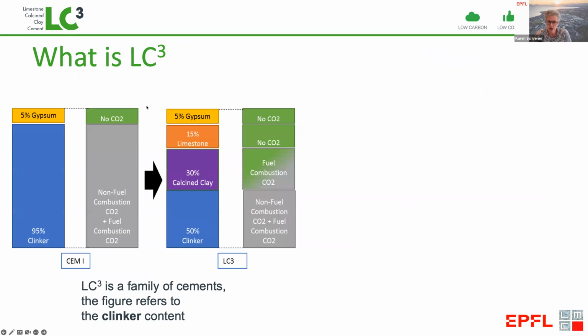Now, the reason we get this much lower CO2 is because we replace the clinker, which has very high emissions. We have a small amount of clinker we still have, but the calcined clay has much, much lower emissions, maybe only 1/10 of the emissions of clinker. And the other ingredients, the limestone and the gypsum, basically have near zero CO2 emissions.